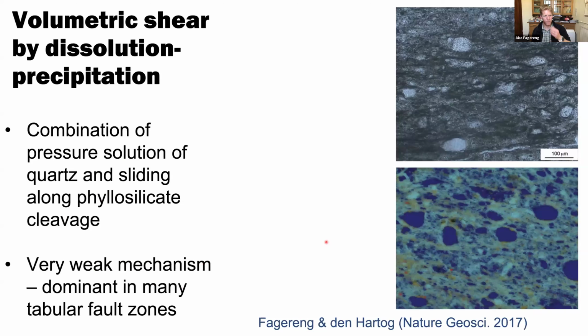So to zoom in on that, thinking about what happens in addition to the fracturing in these melanges, if you zoom in on the matrix, what you generally see is evidence that quartz clasts, here in white, are surrounded by black cleavage planes, which are remnant clays and oxides from dissolution of quartz. So you develop this cleavage system, which stands out a bit more in an EDS chemistry map, where the reds are clays and the blue is silica. So you see that these cleavage surfaces are made up of clays.